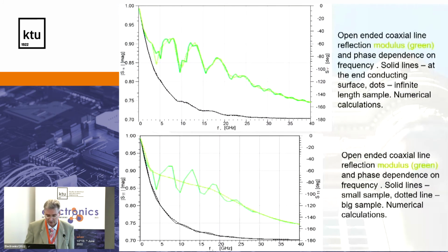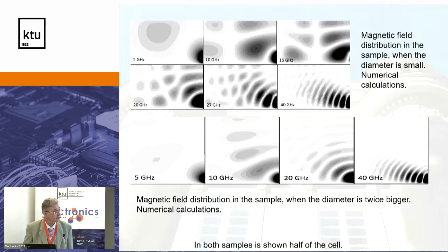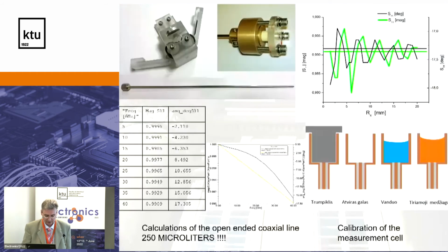And due to that, we developed a method with a magnetic field distribution, which is also interesting, also possible to extract magnetic properties. We developed a method which needs 250 microliters. So a few drops of liquid is enough to tell the electric properties, for ionic liquids, for biological substances, and we can measure up to 40 gigahertz. And the calibration procedure is short, open, standard liquid and unknown material to measure the properties. So that's shortly about coaxial lines.